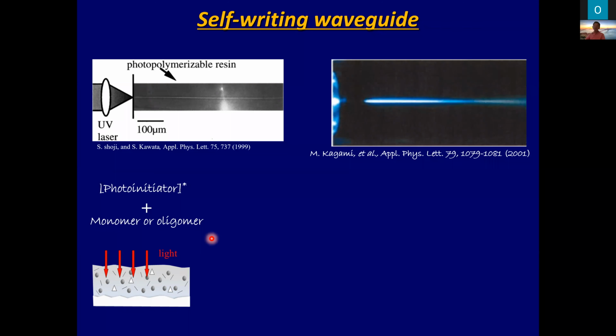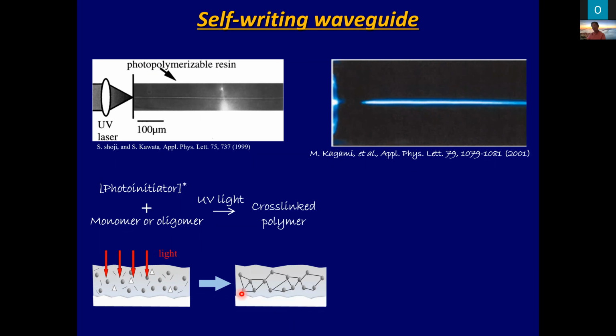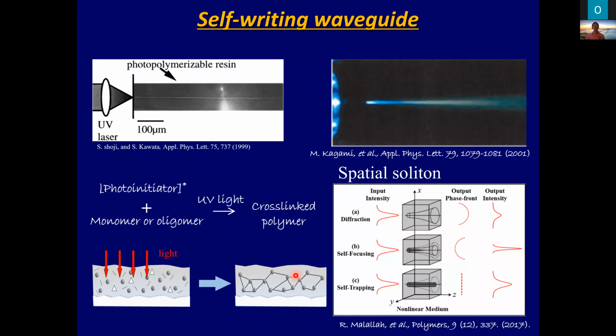The mechanism is quite simple. The UV light attacks the photoinitiator, the monomer and oligomer cross-link, and polymerization occurs. At that moment, the polymerized matter has a relatively higher refractive index. The optical field must be confined, like one kind of non-linearity of the spatial solitary effect, the self-focusing effect. Generally speaking, the optical field suffers from the diffraction effect. But the diffraction effect can be compensated by the self-focusing effect. At that moment, the spatial form doesn't change, even after a long propagation. We want to say this is a spatial solitary effect.